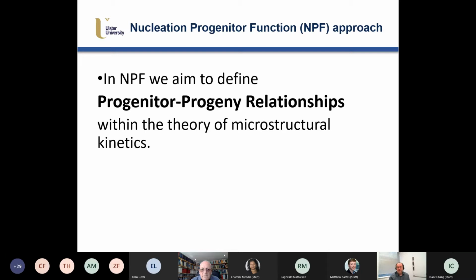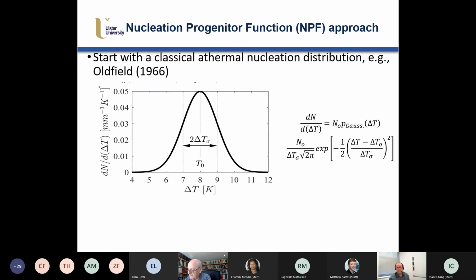So what is the nucleation progenitor function approach? It's new terminology that we've introduced, and what we're trying to do is look at it in a different way, and that will be more instructive. In particular, we're aiming to define progenitor-progeny relationships within the theory of microstructural kinetics. What's a progenitor? A progenitor is a function that describes where all seeds come from, or how all seeds are arranged in the domain. They're assumed to be distributed uniformly following a Poisson distribution, and then you can have any athermal distribution in undercooling.